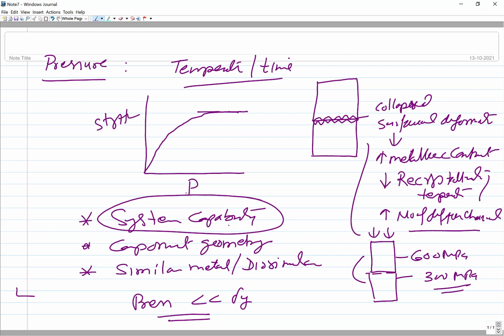So you have seen that the pressure to be applied depends on the metal system to be joined and the surface condition in which the joint is to be made. The rougher the surface, the greater the pressure requirement, so that good metallic contact between the two can be established. Likewise, the higher the strength and the lower the ductility, the greater the pressure required at the diffusion bonding temperature. So the pressure to be applied will be influenced by the surface condition and the yield strength of the metal at the diffusion bonding temperature.